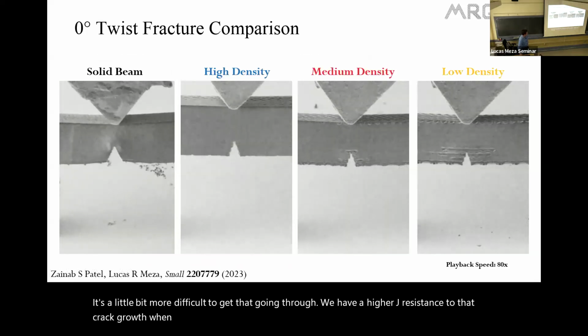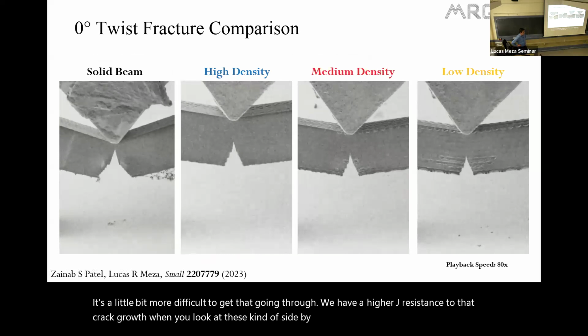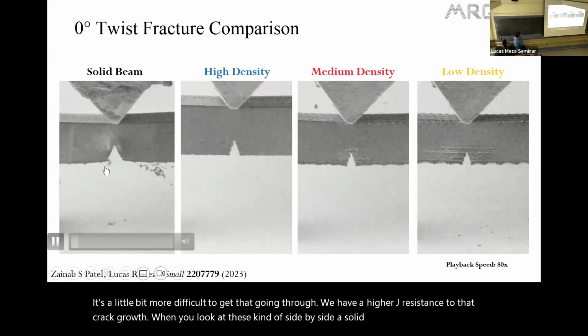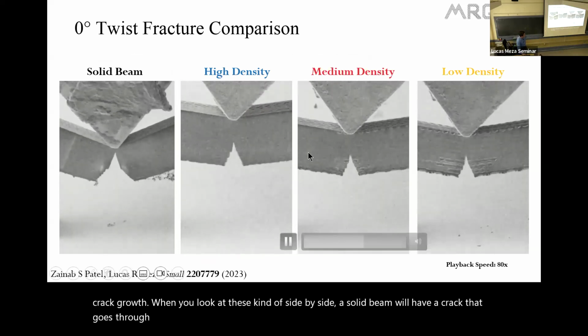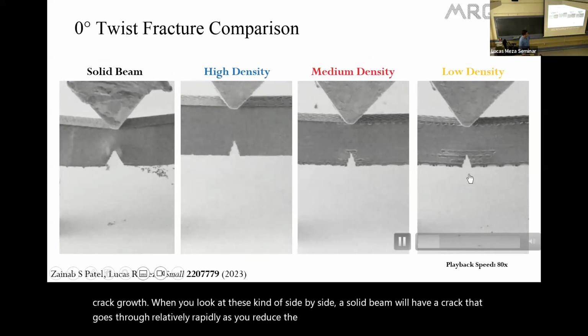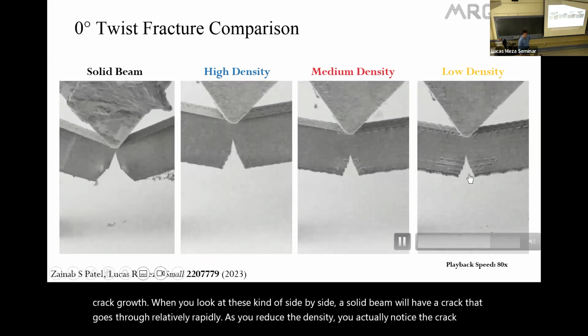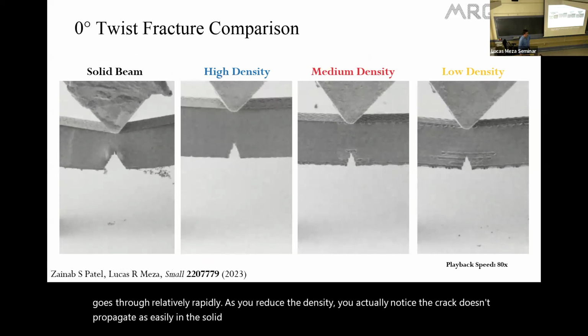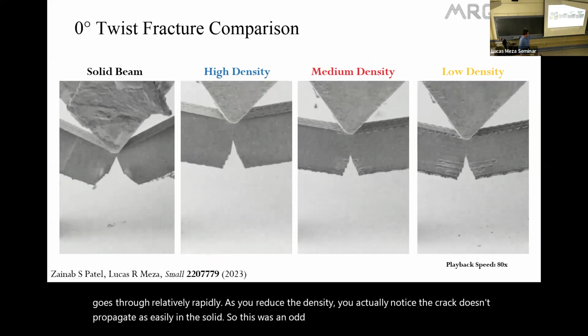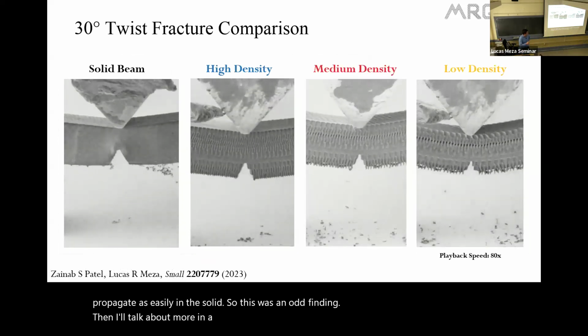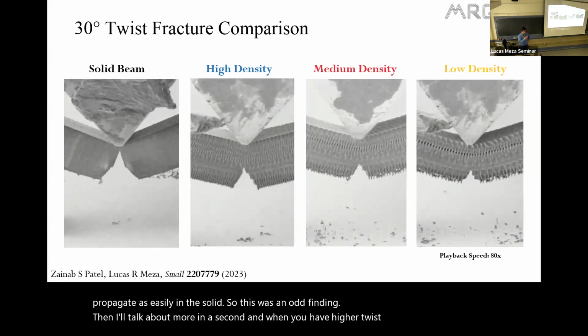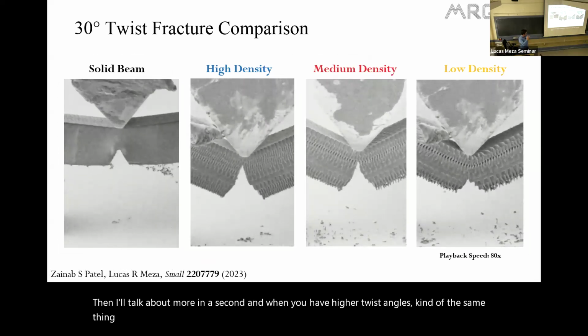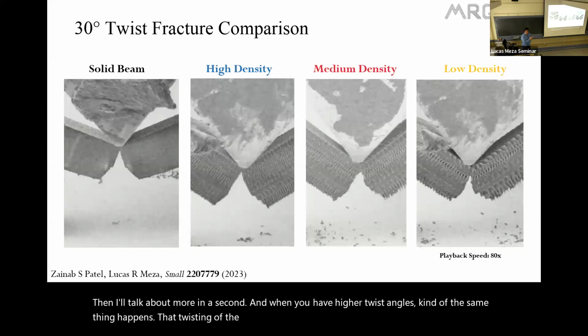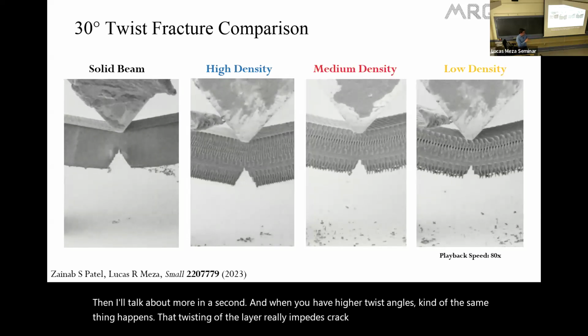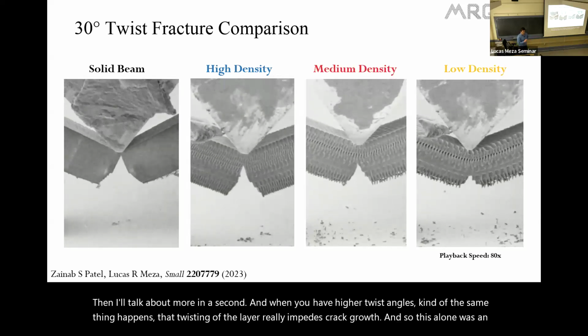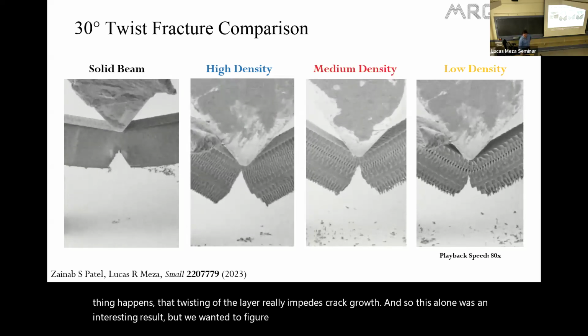When you look at these side by side, a solid beam will have a crack that goes through relatively rapidly. As you reduce the density, you actually notice the crack doesn't propagate as easily in the solid. So this was an odd finding that I'll talk about more in a sec. And when you have higher twist angles, kind of the same thing happens. That twisting of the layer really impedes crack growth. And so this alone was an interesting result, but we wanted to figure out what really was going on here.